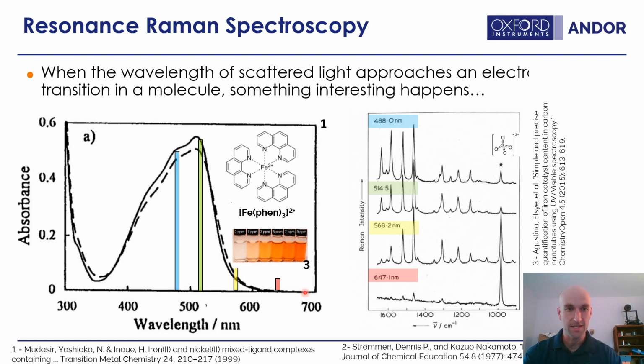So you can see this is an iron coordination compound, or organometallic coordination compound, and it's got a strong absorption here, which is where we're going to promote some electron or electrons from ground state to an excited state. And you can see that this is an absorption in the green. It doesn't particularly absorb red light. Here's yellow, green, blue, very, very blue. And that's where that absorption is happening. That's where it will actually take light and do something with it. It will cause a real excitation in the molecule.